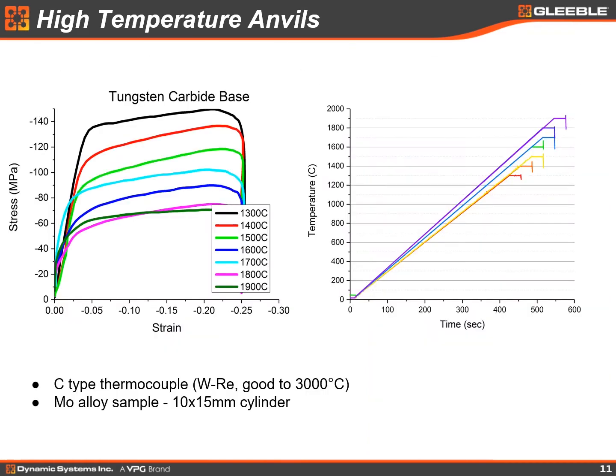Preliminary testing started by simply replacing the anvil cap of the standard anvil assembly with the new high temperature cap. We use C-type thermocouples, the tungsten-rhenium based thermocouples, peened into a molybdenum alloy specimen. Tests are run at 100 degrees Celsius increments from 1300 degrees to 1900 degrees Celsius. Shown here are both the time-temperature plots of these aforementioned tests, as well as the stress-strain data generated from these ultra high temperature tests.